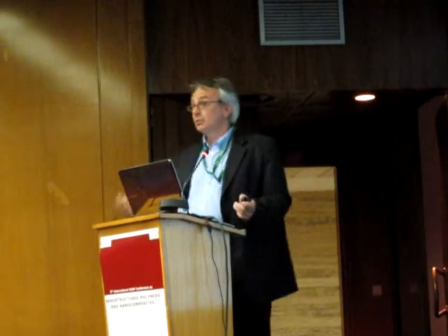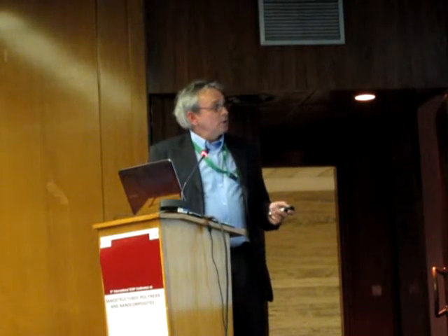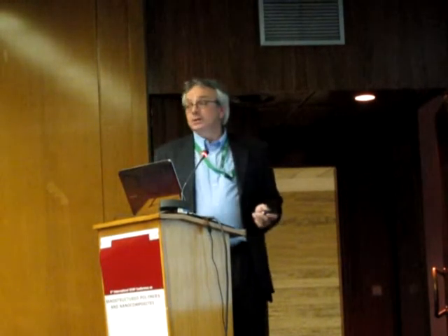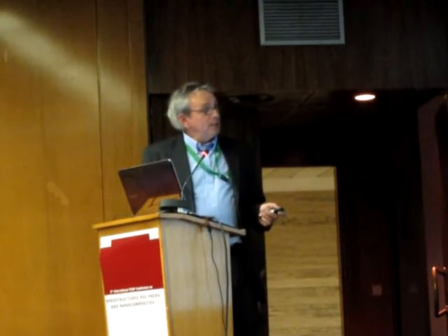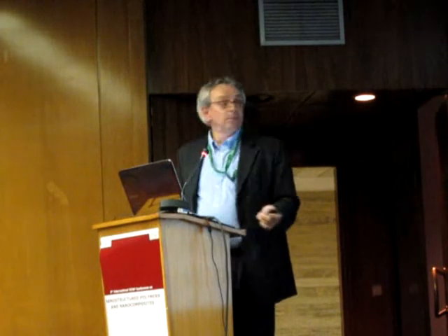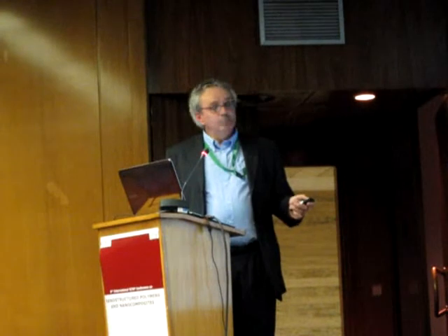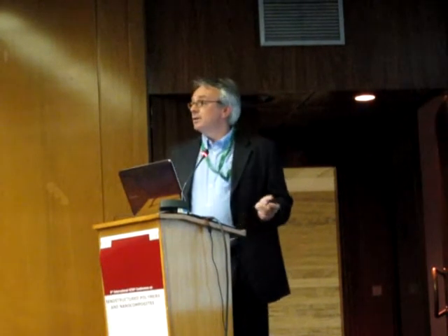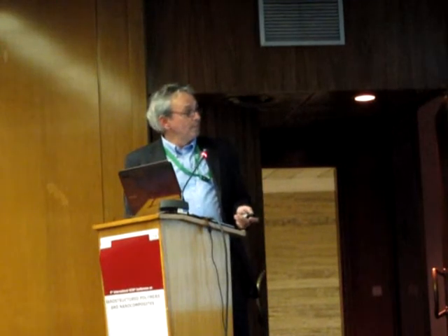But the problem is that you now need to do some chemistry and take care especially of the miscibility with the medium in which you put the system, because you play with what we call reaction-induced phase separation: you begin from a miscible system and precipitate at the nanoscale an inorganic rich phase into the system.